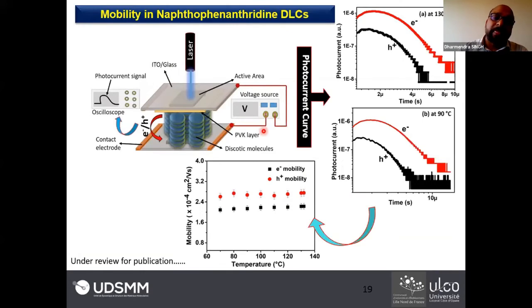There is one important demerit in some discotic liquid crystals, because sometimes these materials do not absorb the light completely near 355 nanometers. When the laser absorption is not sufficient, it is not able to produce sufficient excitons, electrons and holes that can propagate from the top electrode to the bottom electrode. To cope with this problem, we coat a photosensitive layer of PVK over the top electrode, so that this top electrode is able to absorb the laser light, and after that it injects the charge carriers into the materials, and the charge carriers, electrons or holes, propagate from the top to bottom electrode under the particular applied voltage. So that is one problem in this.